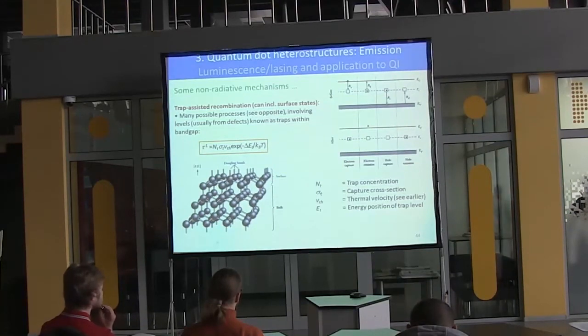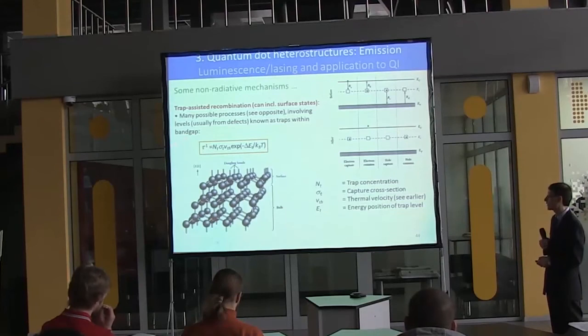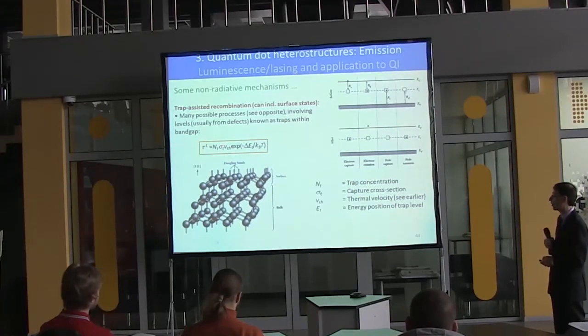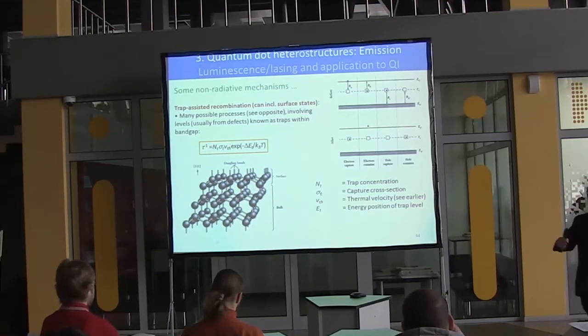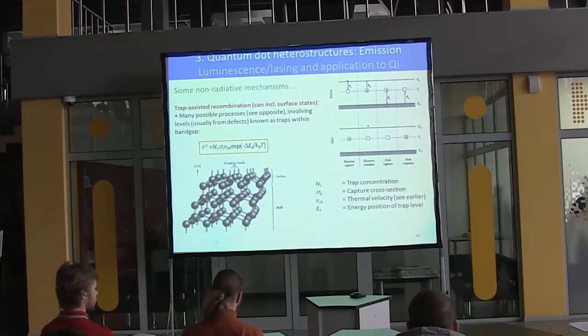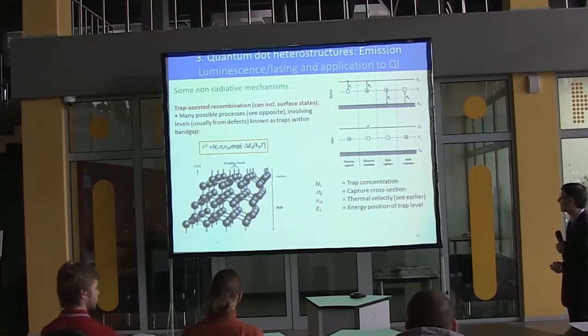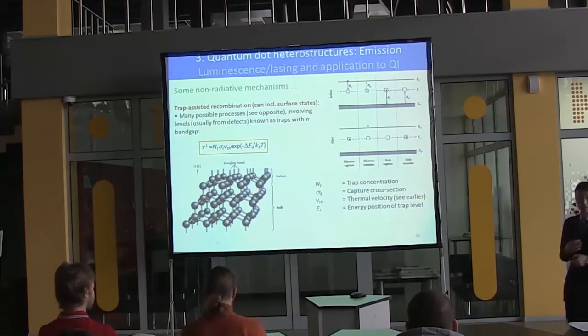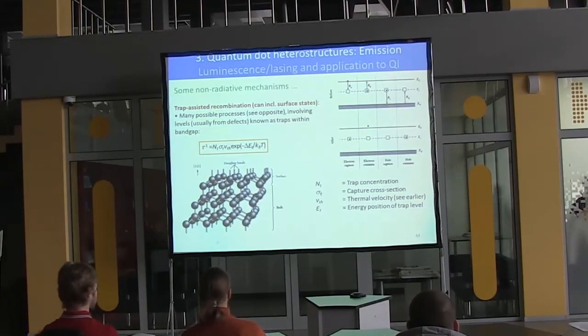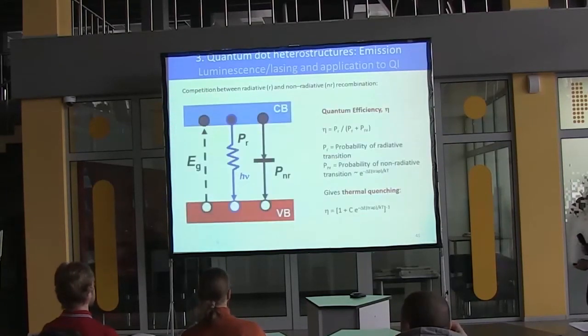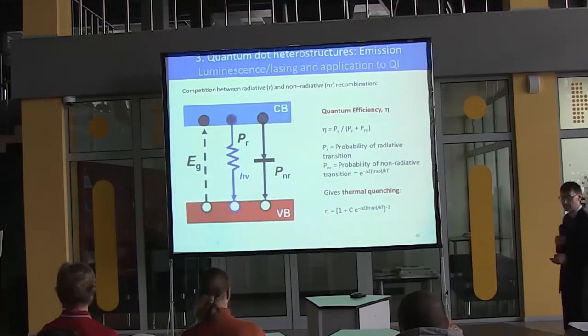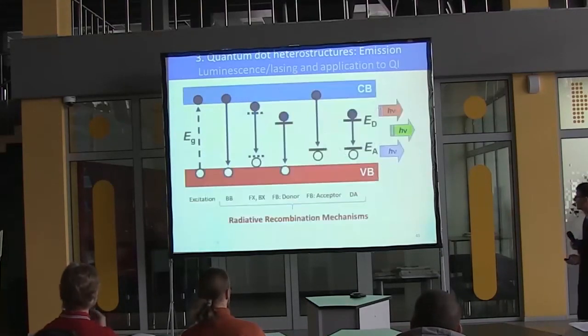the recombination. And you can have trap-assisted capture and recombination, and the basic story of that is that the rate, which is 1 upon tau, 1 upon the time it takes to recombine, will go with how many traps you've got, which means the areal density of these nasty things. It will go with the capture cross-section, which is essentially where the local field is that's dragging something in. And it will go with the activation energy, which basically means the work required, or how deep the trap is, if you like, with respect to its ionized state. All right, so that came back to the trap idea, and that gives you all the radiative recombination things you need to look at.